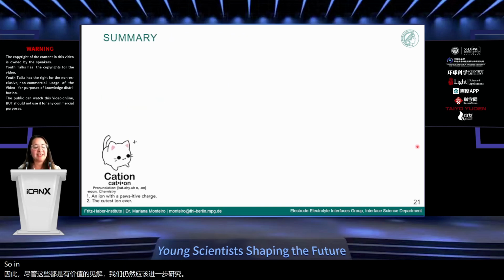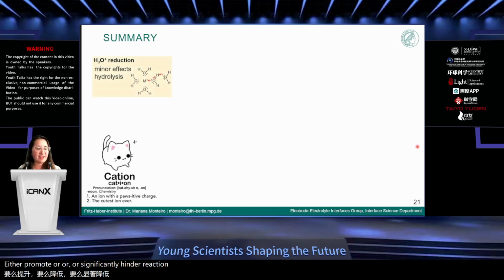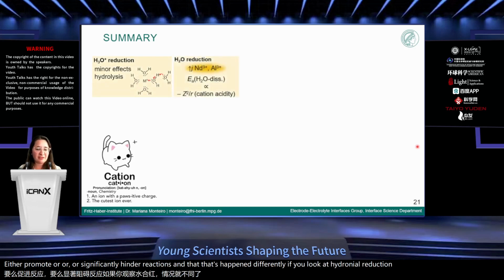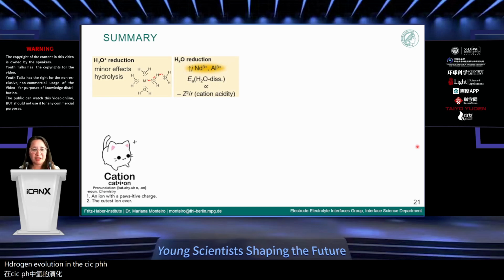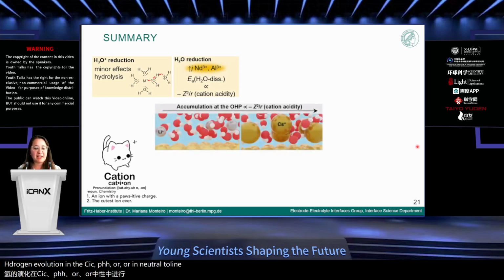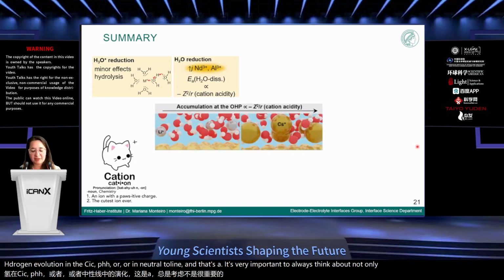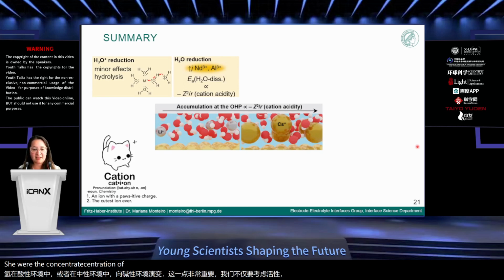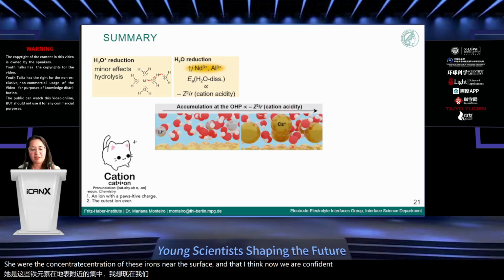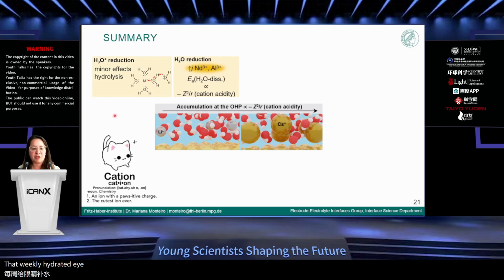So in summary, I hope I convinced you that cations are important and that they can either promote or significantly hinder reactions, and that happens differently if you look at hydronium reduction, so hydrogen evolution in acidic pH or in neutral to alkaline. And that it's very important to always think about not only activity, but the concentration of these ions near the surface. And that I think now we are confident, especially with the surface XRD data, that weakly hydrated ions accumulate much more at the interface.